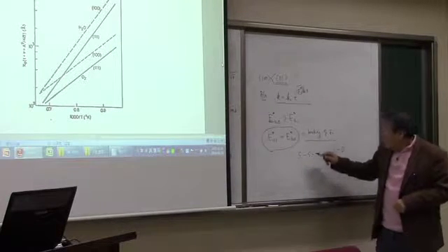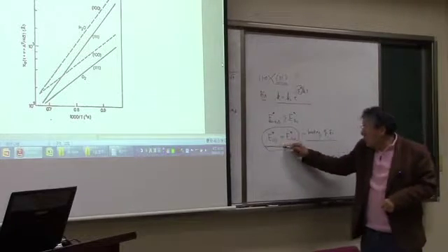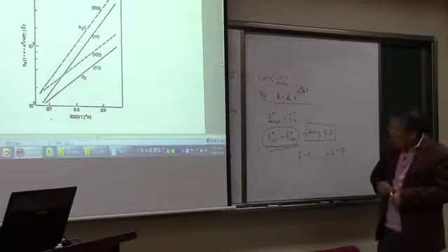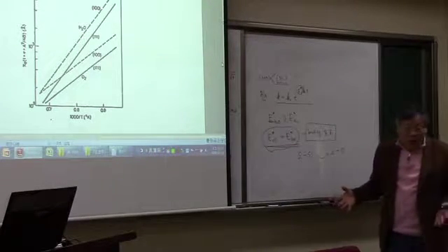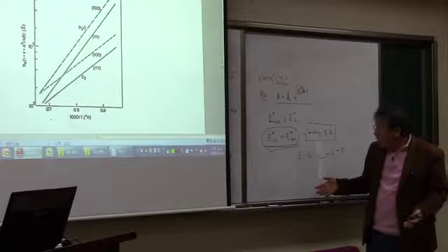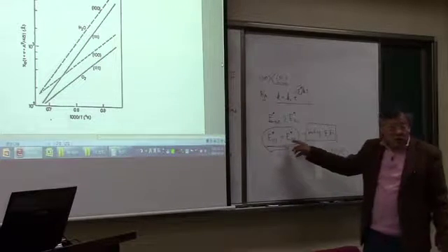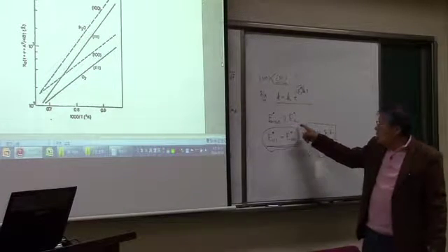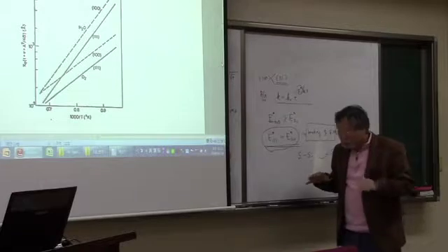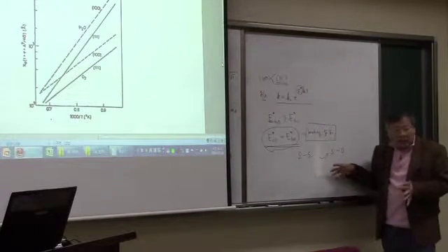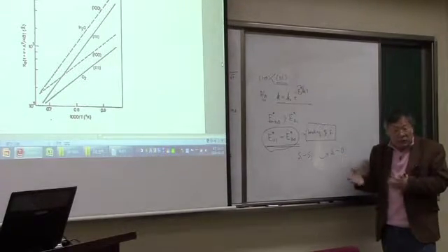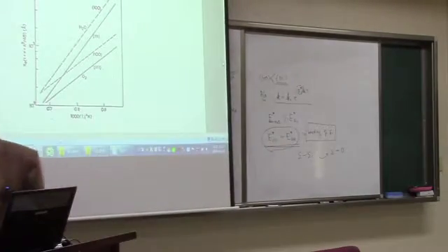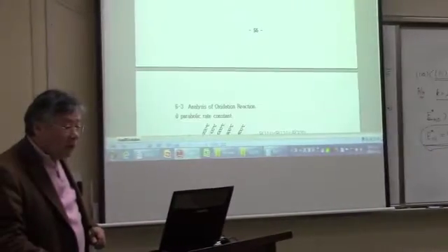So this activation energy should be related to the bonding energy of the silicon, so no matter what the atomic density is, the activation energy should be the same. But depending on the environment, H2O or O2, the efficiency of breaking the bonding is different. So that's what we can see in this figure.